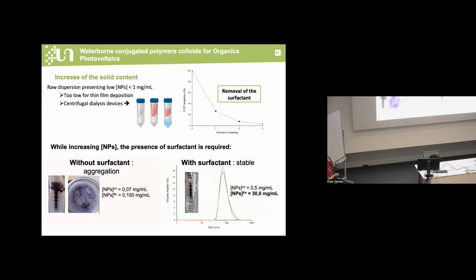So then we could show how important is the presence of the surfactant. What we get is a low concentration of raw material, here around 0.5 milligram per milliliter. And in order to increase the concentration of material, we use centrifugal dialysis. And when the surfactant is not present, you can see here on the left side of the slide that aggregation occurs. Whereas when the surfactant is in the dispersion, you still get stable nanoparticles of about 30 milligrams per milliliter. And here I present that we could remove the excess of surfactant by using several cycles of